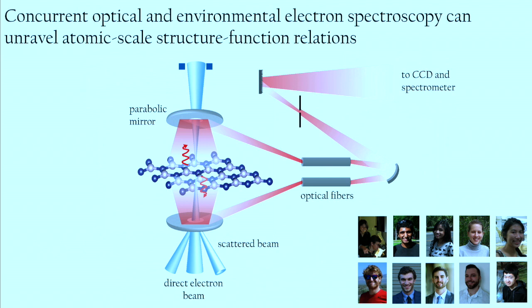And what we've done is capitalize on a lot of the spectroscopies and approaches that are already in place in the TEM, but also modify it with additional capabilities, in particular the addition to couple light into and out of the transmission electron microscope. So we partnered with Gatan a few years ago to develop the Vulcan holder, where we can take our electron transparent sample that's in the transmission electron microscope and then surround it by two parabolic mirrors. And the holder actually has two fiber optical inputs or outputs, so that way you can either do illumination or detection or dual illumination and detection of your materials.